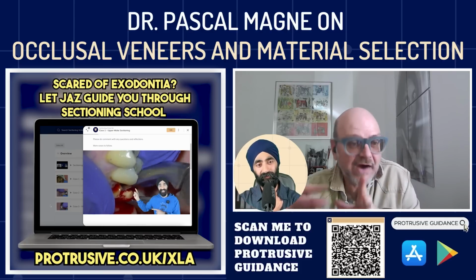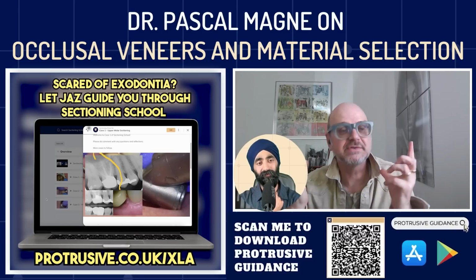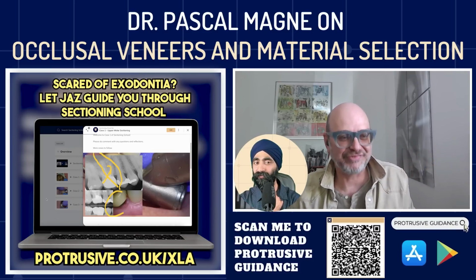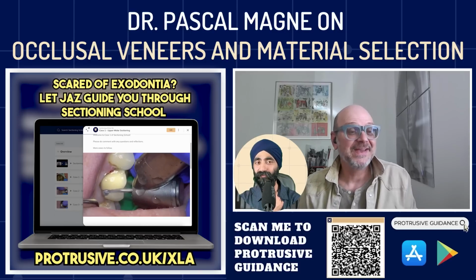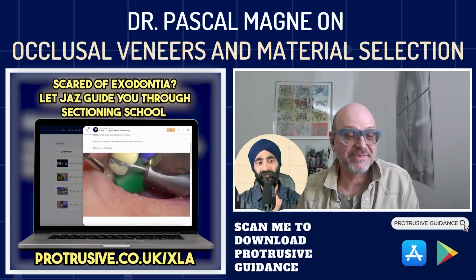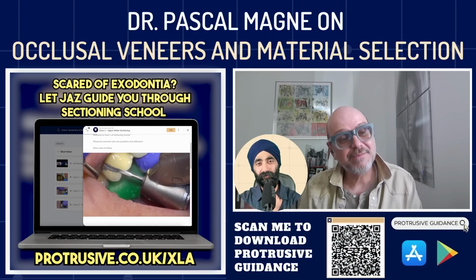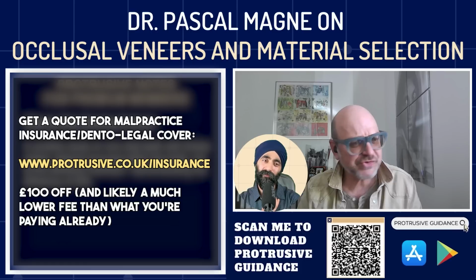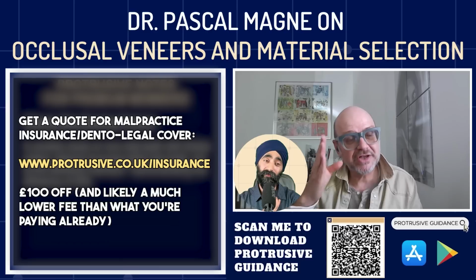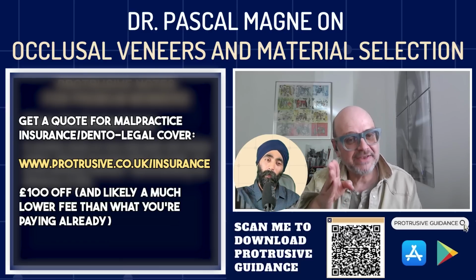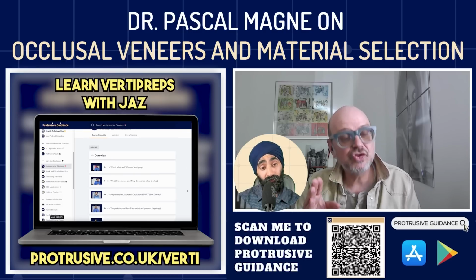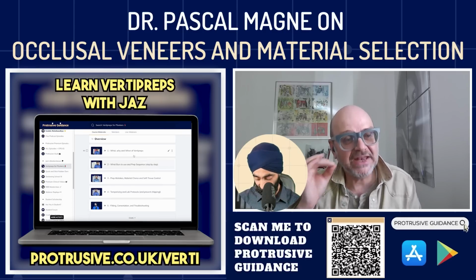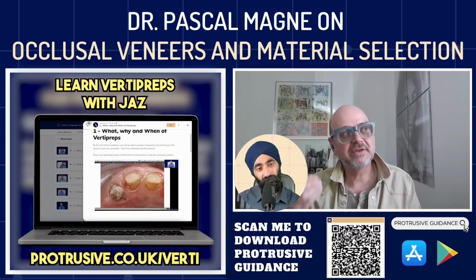That's how we did in our study, where those occlusal veneers were unable to fail, if you want, because of the extreme strength of the bond. In the other study about the non-vital teeth with the thicker onlays, what was really amazing is IDS was so efficient that when those onlays broke, the fracture went from the restoration into the tooth straight. There was no failure of the bond. And we took the teeth